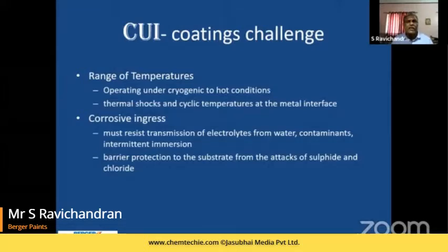For a long time, inorganic zinc silicates had been a product of choice for any area under insulation, because inorganic zinc silicate, for its sacrificial nature, was able to give excellent corrosion protection, as also an opportunity to take a higher temperature of up to 400 degrees. But quite adversely, what has happened under this situation of CUI is that zinc will switch its potential when the temperature crosses more than 80. So instead of zinc sacrificing, the iron underneath becomes an anode and starts corroding. So this is where the challenge was learned over a period of time, and that is where new products came into the picture.